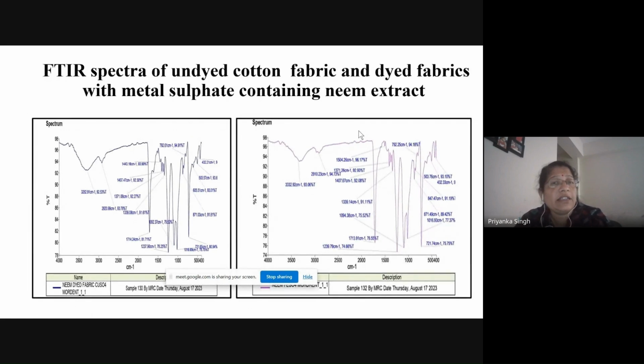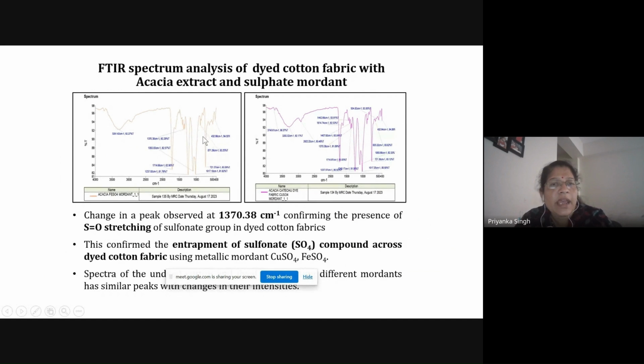But when we treated this cotton fabric after dyeing with the metal sulphate containing neem extract, we can observe a very sharp peak near 1371. Similarly, we have observed a similar peak for the acacia, a specific peak near 1370 here and here also. These both functional groups show the presence of SO stretching. This shows that our dyed fabrics have been entrapped with the sulfonate group. So this confirms the entrapment of the sulfonate group from the mordant into our specific dyed fabric.